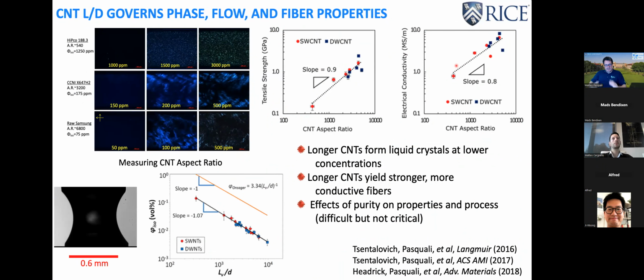How did we get the properties? It's very similar to what happens with polymers. If you want better properties in polymers, you have to have higher molecular weight polymers. And here we found the same science. Initially, we were getting low properties because our molecular weight was low. The aspect ratio, which is the length of a nanotube divided by the diameter, was too low. But with time, we learned how to make longer and longer nanotubes. And this is not just my group, but a community. And my group was the one who really established this scaling, that your properties almost scale linearly, both mechanical and electrical properties. And so as you make longer and longer nanotubes, you get higher and higher properties.